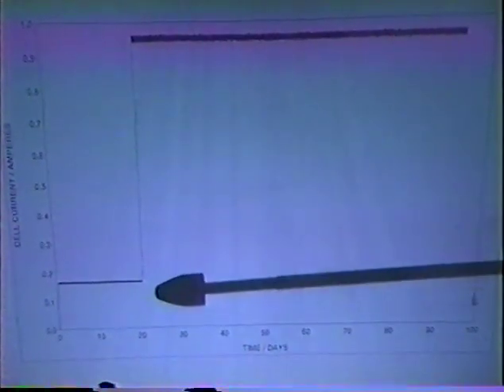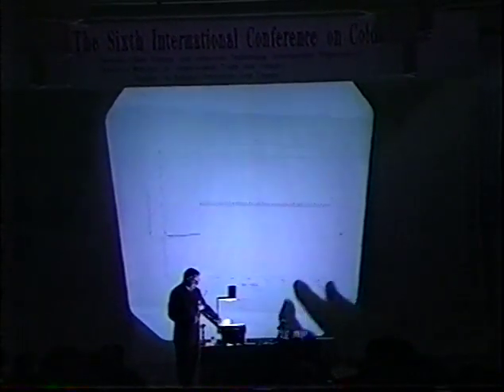same for all experiments. You maintain a constant current, and at some point after you've charged for a very long period of time, similar to the way some of the other experiments you've seen in today's lectures are performed, we then step the current to a higher value and observe the long-term effects. The potential, of course, is measured during the same experiments.